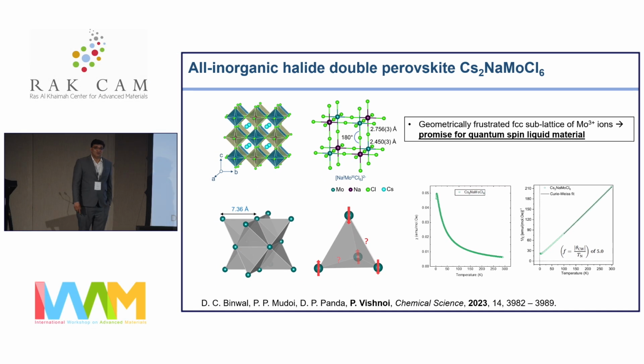We don't see this compound showing any phase transition, at least in the temperature range from liquid nitrogen to high temperature. That means it's a very stable lattice. But essentially what I want to highlight here is the lattice. If I just consider the molybdenum metals and make a diagram like this, we see there are tetrahedra with the corners occupied by molybdenum metal, each of which has 3 unpaired electrons.